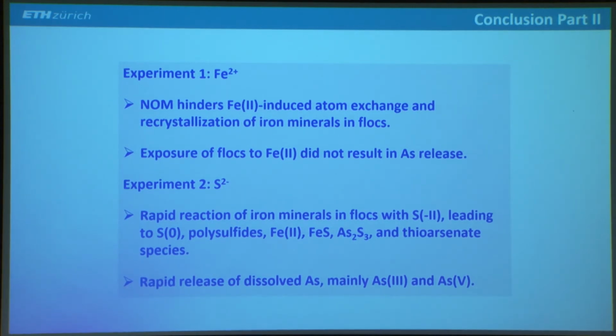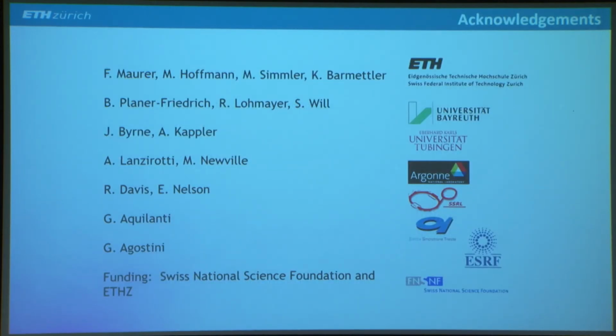So it shows that if there are sulfate-reducing conditions and sulfide produced, this could be very reactive and result in the release of arsenic. Of course, it always depends on elemental ratios, and admittedly, we used a fairly high concentration of sulfide here, and it always depends on whether there's enough sulfide available. But with this, I hope that I showed you a little bit what might happen with arsenic in such a peat environment, and I would like to acknowledge